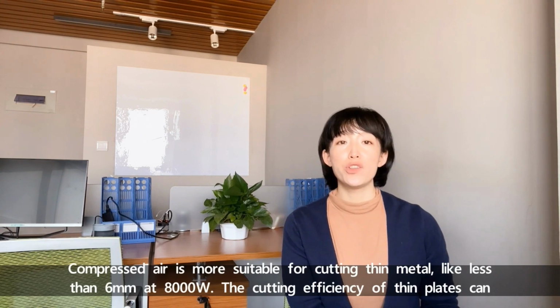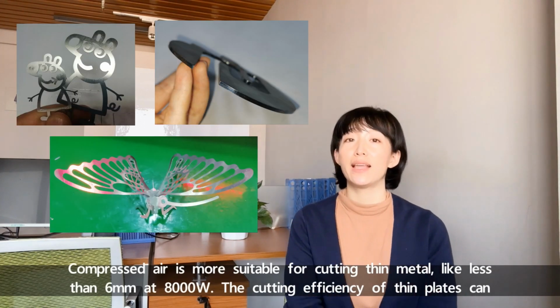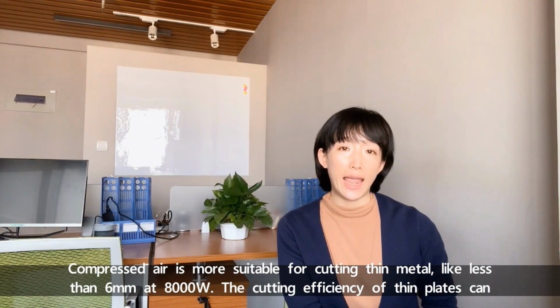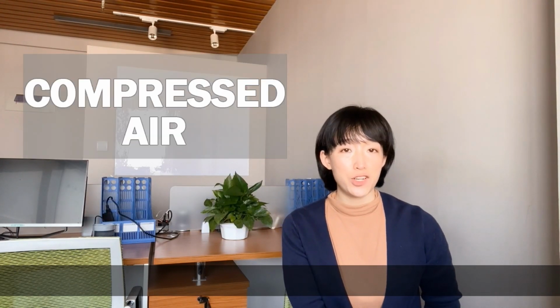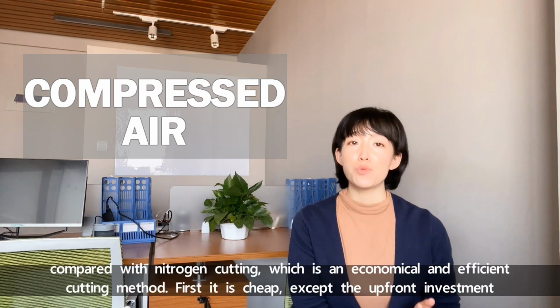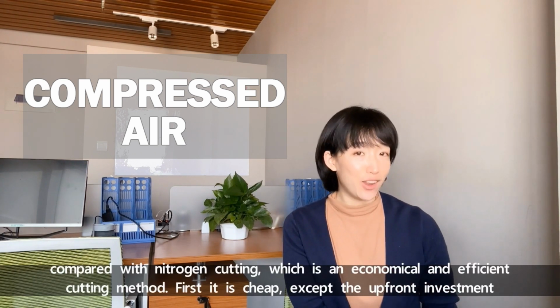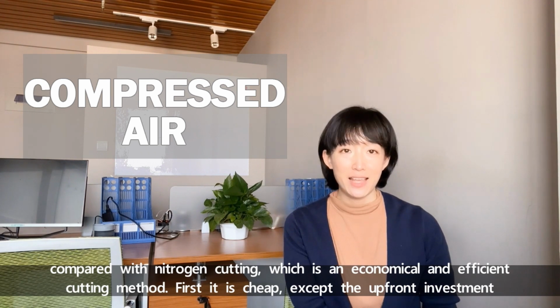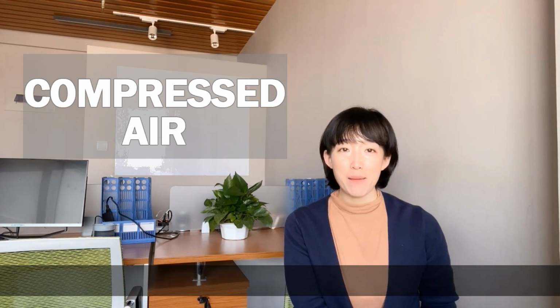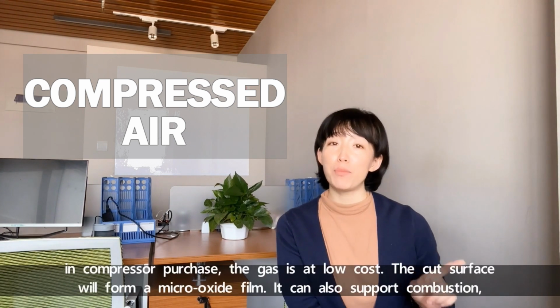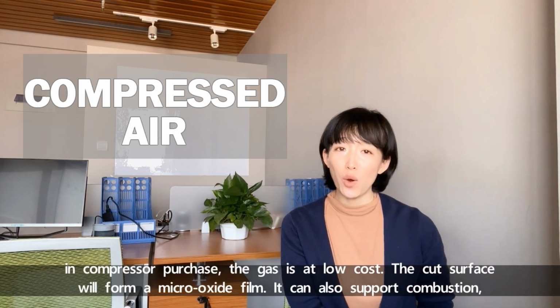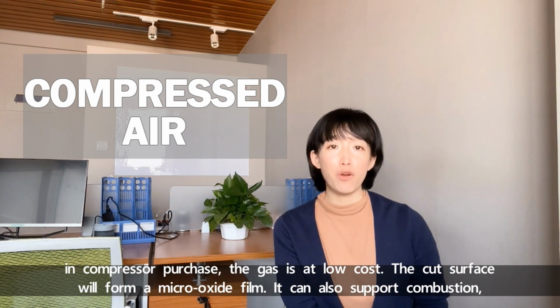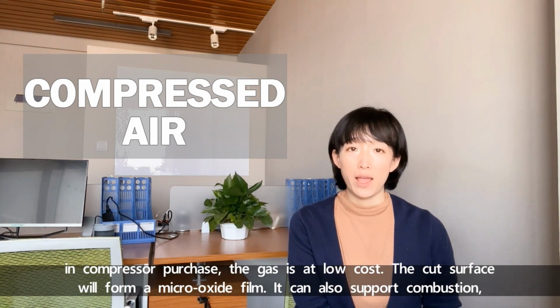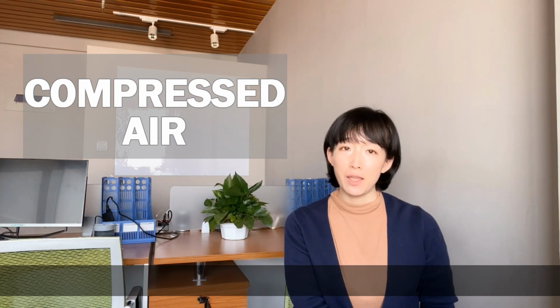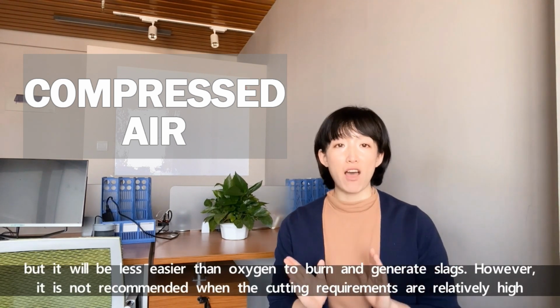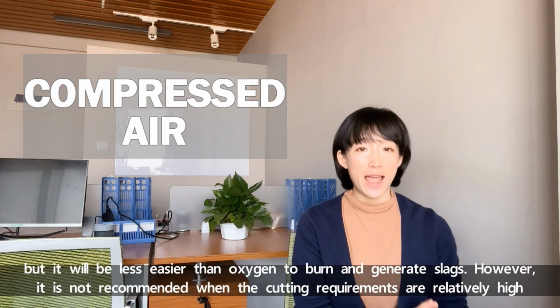Compressed air is more suitable for cutting thin metal, like less than 6 mm at 8000 watt. The cutting efficiency of thin plates can be compared with nitrogen cutting, which is an economic and efficient cutting method. First, it is cheap. Except for the upfront investment in compressor purchase, the gas is low cost. The cut surface will form a micro oxide film. It can also support combustion, but it will not burn and generate slags as easily as oxygen.